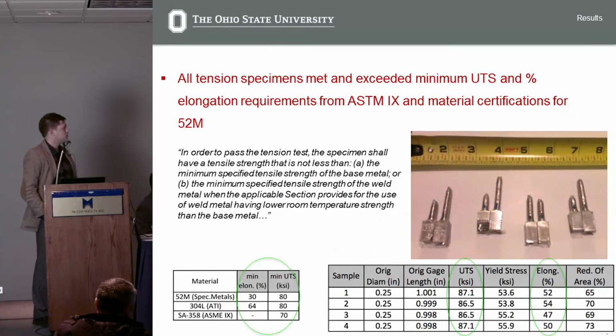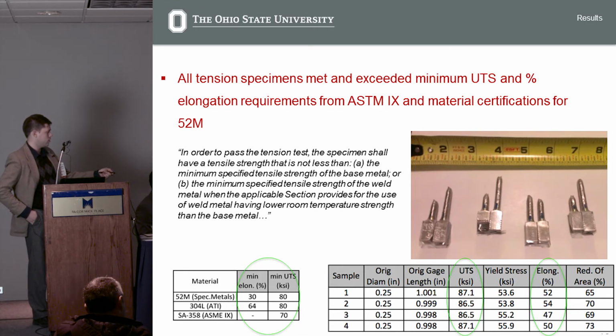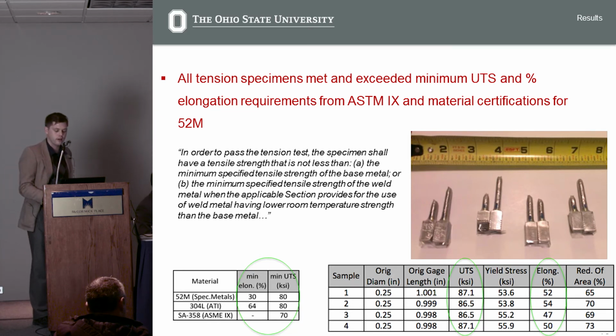And tensile testing revealed that all the tensile specimens met and exceeded the ultimate tensile strength and percent elongation requirements for Section 9. We can see here that the Special Metals specification for the 52M is 30% elongation and 80 KSI tensile strength. And all 4 specimens here met and exceeded those goals, as well as the 304 base metal. The 52M also outperformed the base metal, which was also required by Section 9.